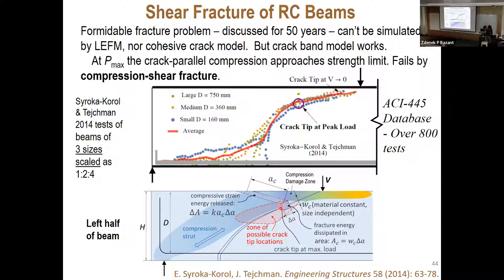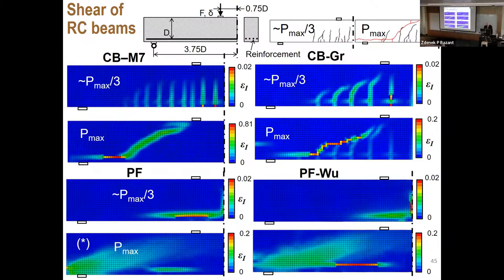It fails by compression shear fracture, which is a band of axial splitting cracks, which propagates from one side to the other, and there also the fact that this area of energy release grows is a side effect. So that's now finally, with the crack gap test, fully understood. Now these are some simulations. So when you simulate it, you first get many cracks. This is in experiments. But then at maximum load, they localize to one dominant crack, always like this, like the red one. So this is 1/3 of the maximum load. You see distributed cracks. At maximum load, you see this diagonal crack.